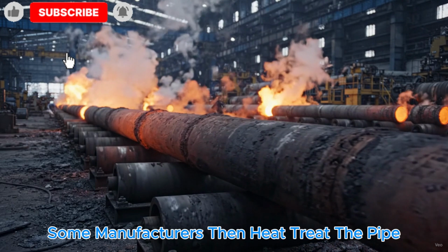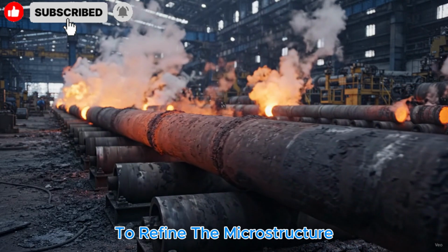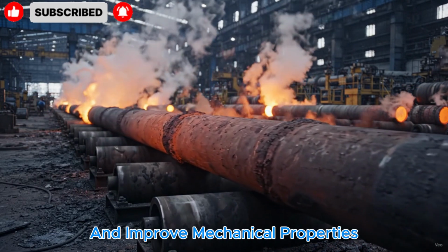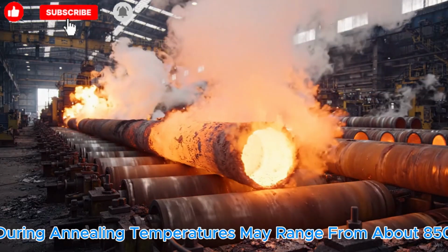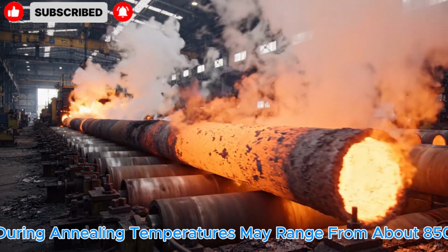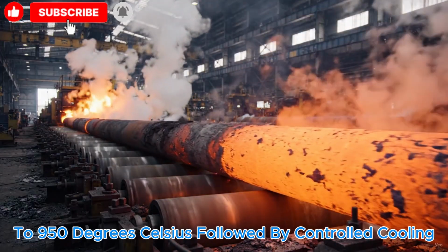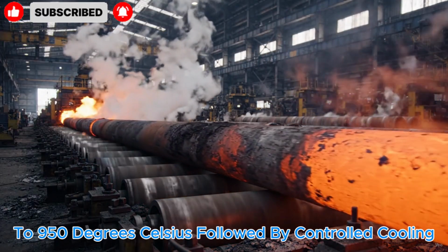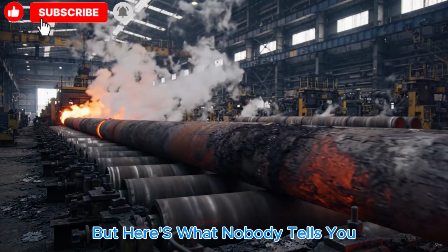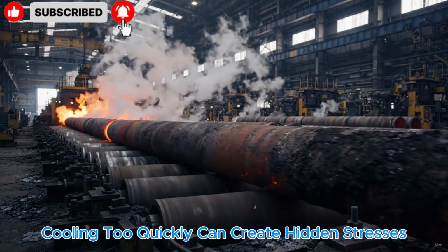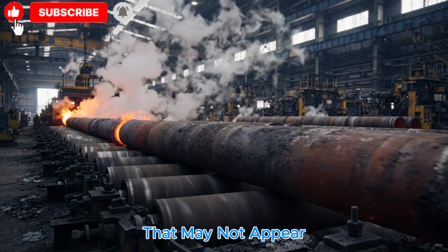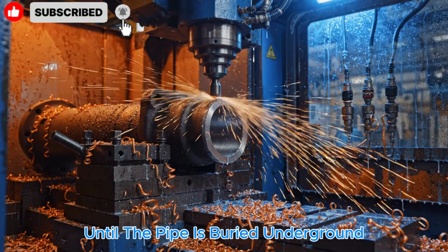Some manufacturers then heat treat the pipe to refine the microstructure and improve mechanical properties. During annealing, temperatures may range from about 850 to 950 degrees Celsius, followed by controlled cooling. But here's what nobody tells you. Cooling too quickly can create hidden stresses that may not appear until the pipe is buried underground and subjected to